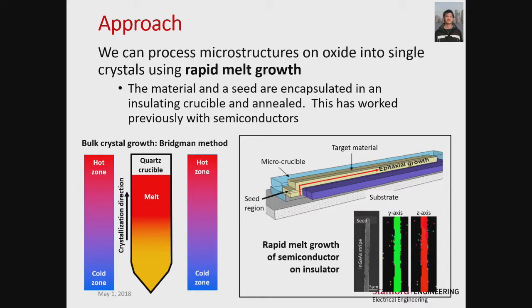A breakthrough came through the labs of my collaborator, Jim Plummer, when he proposed the use of so-called rapid melt growth, whereby some of these concepts could ultimately be scaled on a chip. Furthermore, these methods do not require a temperature gradient like these or other zone refining techniques. Rather, this only requires uniform temperatures. The way this works is that you put, in this case, semiconducting material on a lattice matched or crystalline substrate.